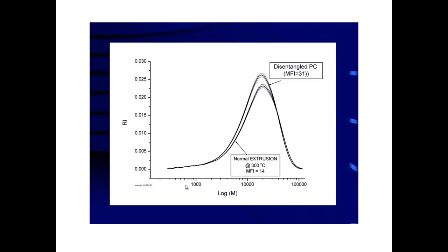Plus, you would not see a recovery. In other words, as you will see in the following slides, the process is recoverable, and if you let temperature anneal the melt, it is gaining in viscosity and trying to return back to a stable value which has a higher viscosity, not a lower viscosity. So if you had it plasticized, it would not be a reversible effect. Same thing for branching. If you have some branches, and sometimes you do create branches, it would still limit the value of the lower Newtonian viscosity, but not if a melt is capable of going back to its initial viscosity. So it would not explain that.